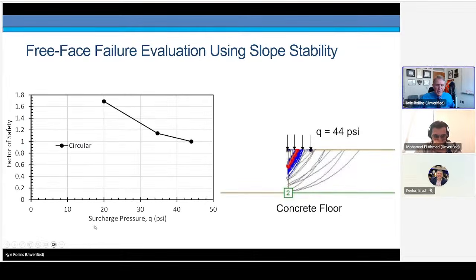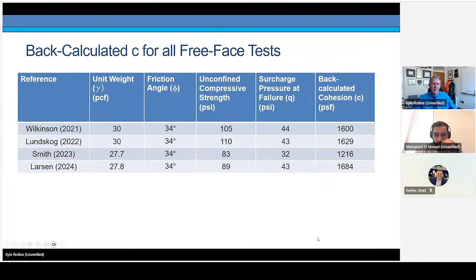Then we started increasing pressure, and to get failure, we have to increase the pressure to about 44 psi, which is what we measured in the field. And these are the critical failure surfaces for that case, and agrees reasonably well with what we saw in the test. So that gave us some confidence that this might be a valid approach. We had 4 different tests where we had a failure of the free face. And for each of those, we used a friction angle of 34 degrees. There's some differences in unit weights, differences in unconfined compressive strengths. And we back calculated the cohesion that it would take to have a factor of safety of 1.0.